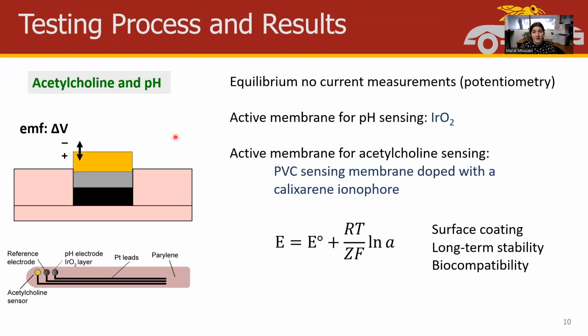The sensing membrane creates a charge separation at the interface, something we refer to as electromotive force, or electrical potential at the surface. And this electrical potential correlates to the natural log of activity of these biomarkers, following the Nernst equation. For pH, we use an oxide coating. For acetylcholine, we use an organic sensing membrane that has a highly stable organic receptor that generates selectivity for acetylcholine specifically. In this part of the project, we modify surface coating, long-term stability, and biocompatibility of these sensors.